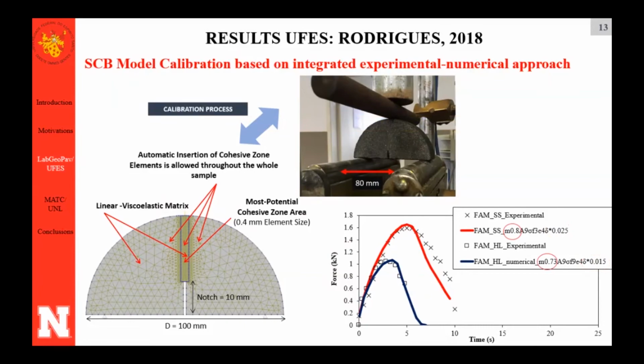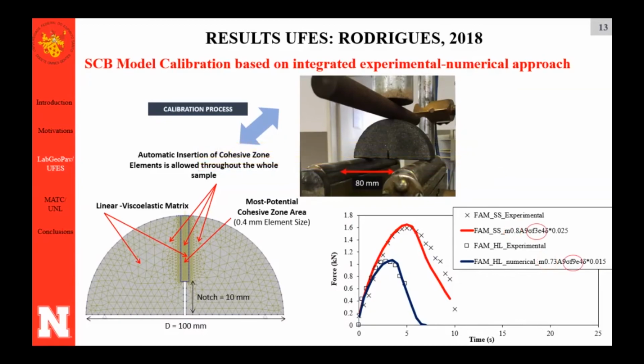So we have an increase on the area under the curve, so it makes the material more ductile. She also observed that the M value decreased with slag 0.8, with hydrated lime is 0.73. That means that the damage propagates slowly on the FAM with slag in comparison with the FAM with hydrated lime. And finally, she saw that the stress initiation criterion is lower for the slag in comparison with hydrated lime.